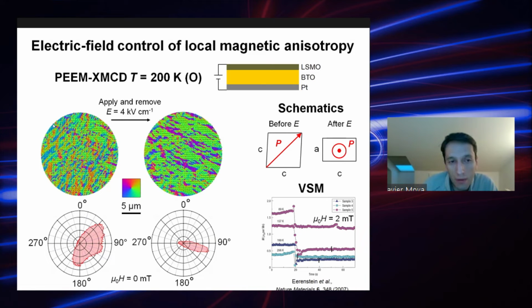So you see, you start with an orthorhombic phase in the substrate, and you have this very complex magnetic configuration. And then when you apply an electric field of 4 kilovolts per centimeter, you see that you can change the microstructure. And if you do a polar plot of the distribution of the moment, you see that here the magnetization is roughly oriented in all directions. So you have this kind of globular distribution. And then when you apply an electric field, you see the magnetization is rotated and aligned along this direction, which is left to right. So it's this gray and purple. So you can actually rotate the magnetization locally with an electric field.